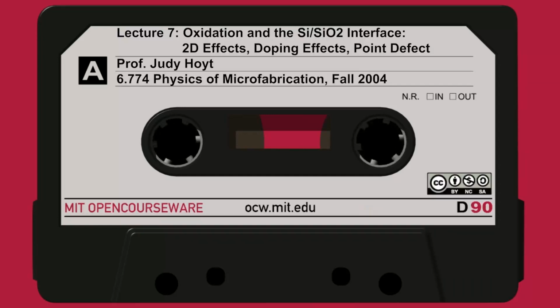Well, this is meant to be a highly schematic picture of a ring structure that would exist in silicon dioxide, where these black circles are the silicon, and we have oxygen here as well, taking up a certain amount of space in the bonds. There is some region in here where there is free space or interstitial space where the oxidant can diffuse through. And let's say P is a hydrostatic pressure in the growing oxide, so there's a certain amount of pressure in the solid.